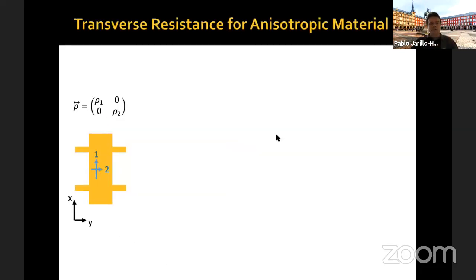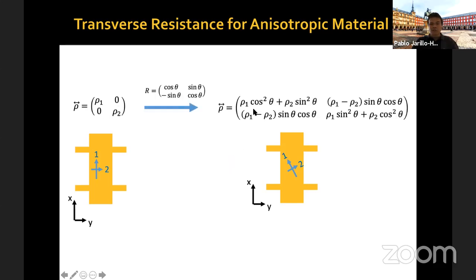So let me tell you the following. Let's imagine you have an anisotropic material, so it's a two-dimensional material. This is the resistivity tensor, with the XX resistivity rho one and the YY resistivity rho two here. Now, if your sample axes, your device axes, are aligned with this anisotropic resistivity axis, then when you measure the transverse resistance, you expect to measure zero at zero magnetic field. However, if your device axis, the way you fabricate it, you have no idea what the orientation is with respect to those anisotropy axes, then you have to rotate your resistivity tensor.